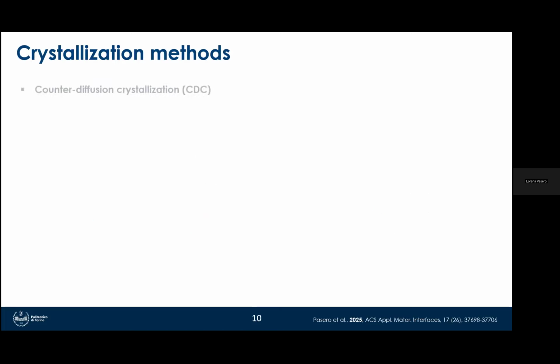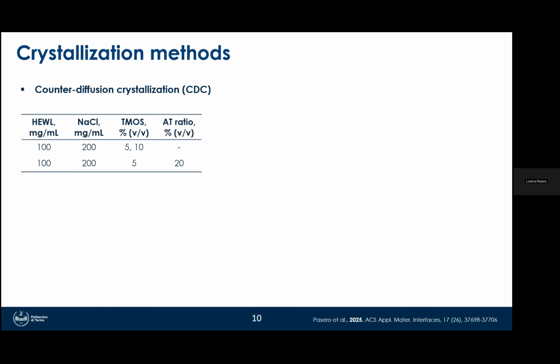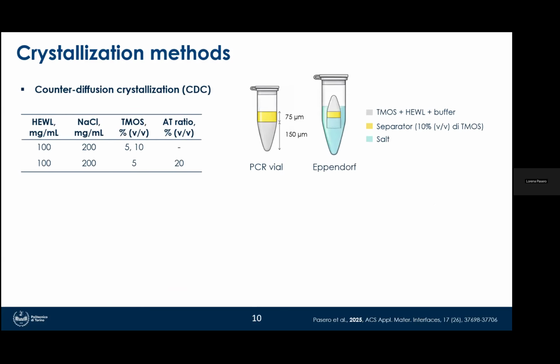To do that, we employed egg white lysozyme as a model protein, and we performed 2 different crystallization approaches. The first one is the counter-diffusion crystallization, where basically lysozyme and the precipitant, which is a salt, are separated by a gel septum, and the salt diffuses in the gel towards the protein. And the second approach instead is batch crystallization, which was here employed on silica gels for the first time.